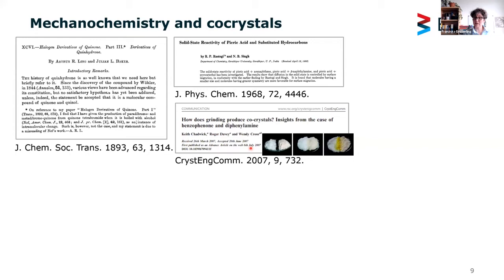co-crystallizations need the formation of a new eutectic in between. You see here the reaction of benzophenone and diphenylamine. It's on a watch glass, and if you just mix it with a spatula, you see here this yellow liquid, that's the eutectic formed. And later on, if you stir it a bit more, then you see really crystallization and you get your co-crystal.